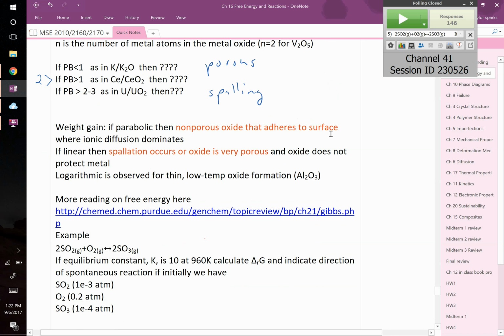is the weight gain, right? So if you take a piece of iron and you expose it to just air, you set it on a scale and you form an oxide, then you're adding oxygen and it's reacting with the metal. So overall, your weight should be going up. You're taking what was pure iron before and you're converting some portion of that iron into iron oxide. So the weight should be going up. So you could actually monitor weight gain this way.